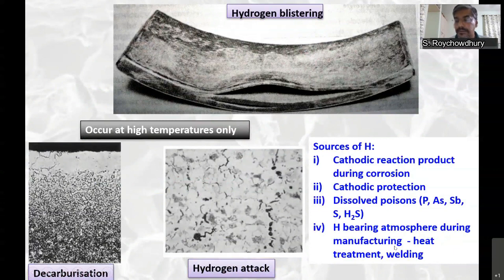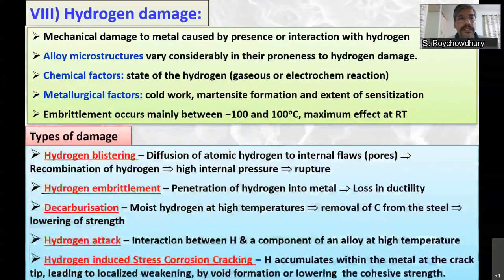During welding and heat treatments, like if you're welding carbon steel plates and the weld electrode flux has moisture present in it, then that moisture can dissociate under welding arc temperatures and generate hydrogen, which can go into the weld metal and cause embrittlement.